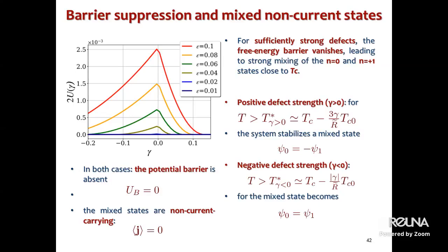Specifically, this is the branching point temperature. This result is for a positive defect: above this branching point, when the barrier has vanished, Psi0 is equal to minus Psi1. Amplitudes are equal, phases are different. In the negative case, they're exactly equal. So if they're exactly equal, due to the potential barrier vanishing, these mixed states do not carry any current. So we do not have any current. So if we work here, the switching effect is 0.